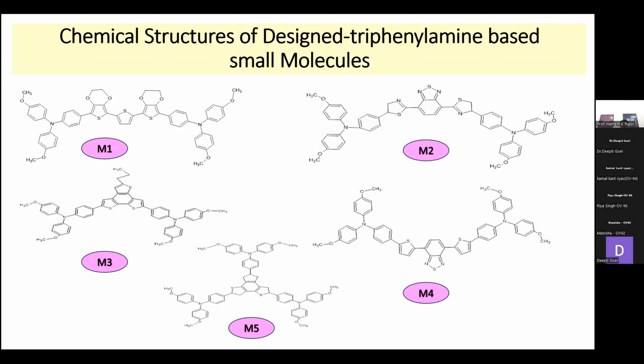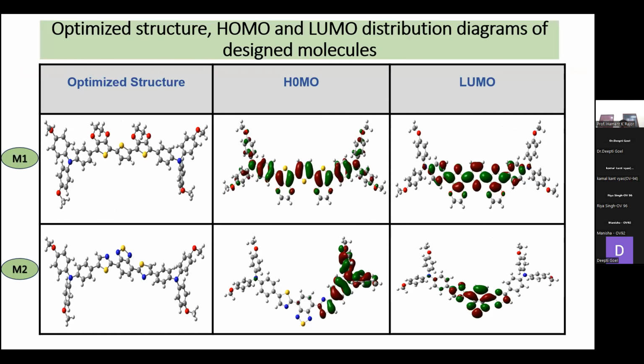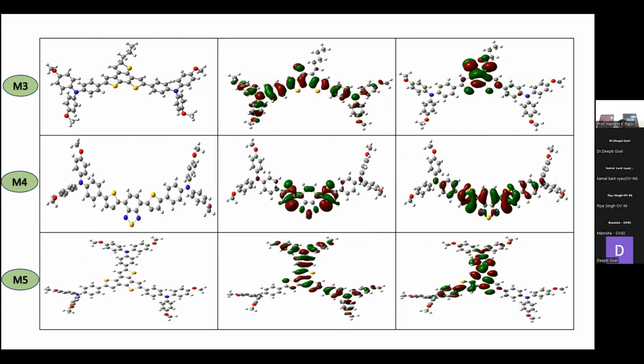Now, all the calculations I have done are using DFT, using the B3LYP hybrid functional. So if we first look at the HOMO and the LUMO structure for these particular molecules, here what we check is the distribution of charges. We can see for M1 it is distributed nicely over the whole molecule, whereas for M2 it is at one corner specifically, and for the LUMO it's at the center only. If we talk about M3, M4, M5, we can see M3 is comparatively better than the other two. As a whole, I think M1 and M3 we focus on more. They have the more distribution throughout the structure.